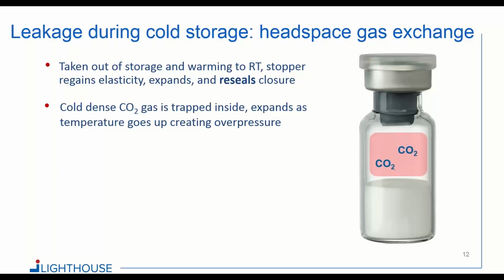That previous reference that I had on one of the slides describes a situation of a viral vaccine, and one of the signs that they had that told them something might be wrong is this overpressure when an administrator took a syringe and put the syringe into the rubber stopper after the vial had thawed. They saw the plunger rod shooting up, and when they removed the syringe from the rubber stopper, you would have live viral vaccine products spraying out through the puncture hole. So not a good situation there. And again, from the ideal gas law, you can calculate that theoretically you could build up an overpressure of about 1.5 atmospheres inside the vial if you're storing at -80.